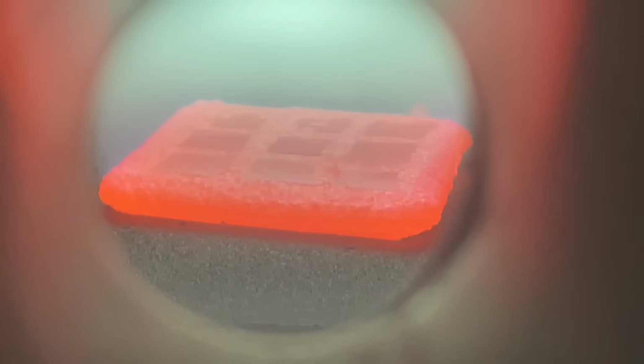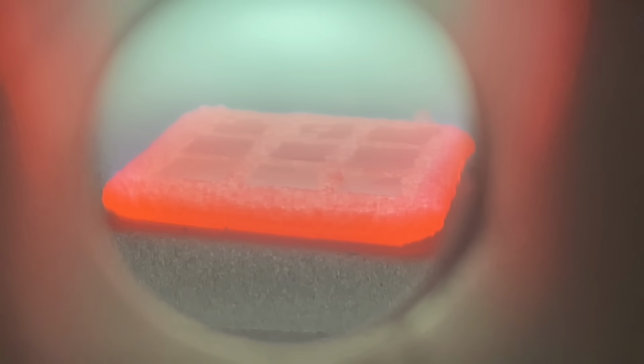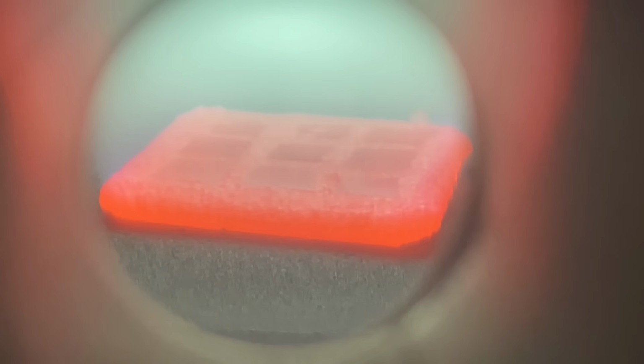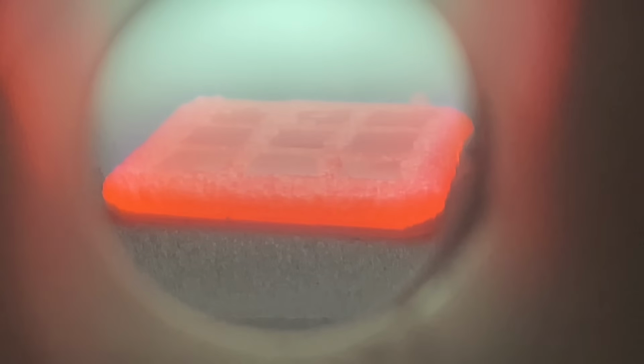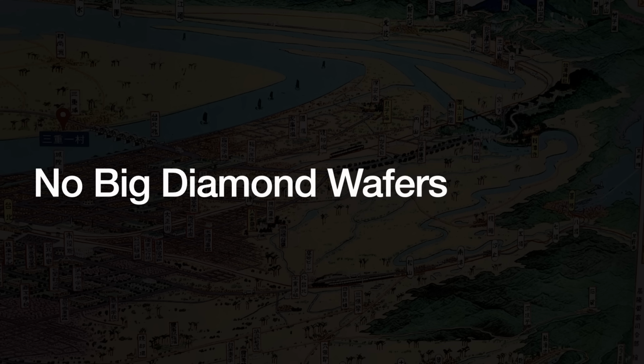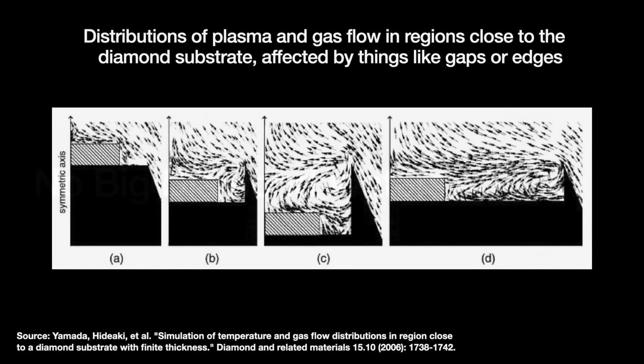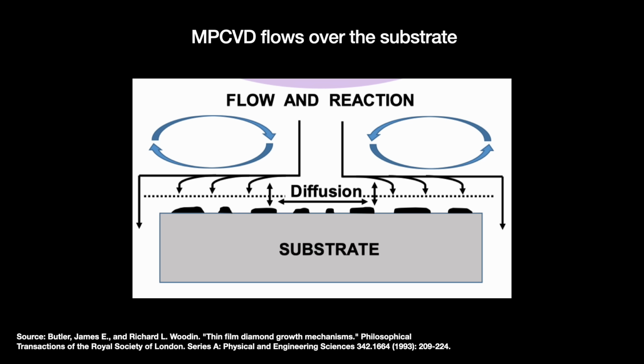Commercialized in the 1980s, MPCVD is the dominant method of producing gem-quality diamond at scale. I once visited an MPCVD laboratory in Taichung trying to produce electronic-grade synthetic diamond, and thought it was pretty cool technology. However, more work needs to be done. The first problem is getting the MPCVD growth rate up without compromising on the quality of the grown crystal. The microwave plasmas are inherently non-uniform, and their flow over the growing diamond surface changes due to subtle things like even the presence of gaps or edges on the substrate carrier. So areas of the wafer experience different conditions, leading to uneven quality.